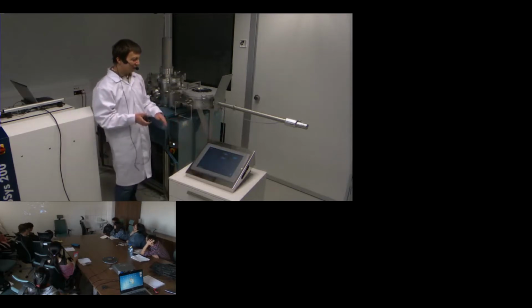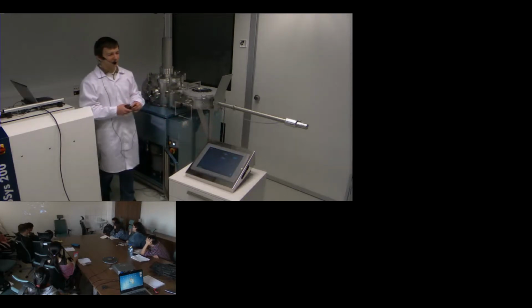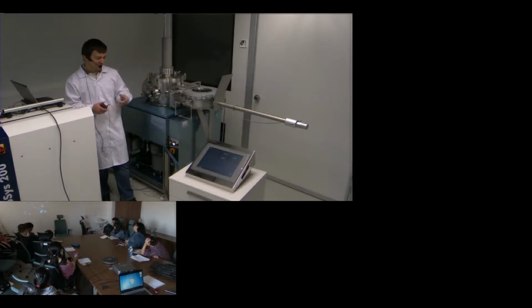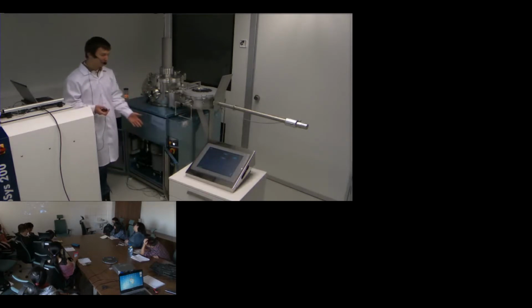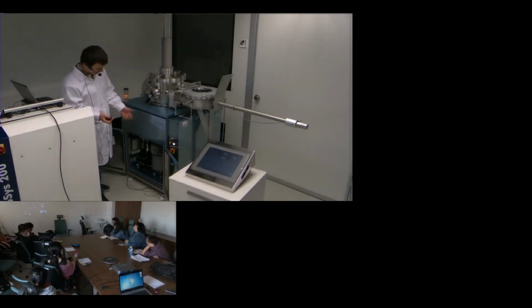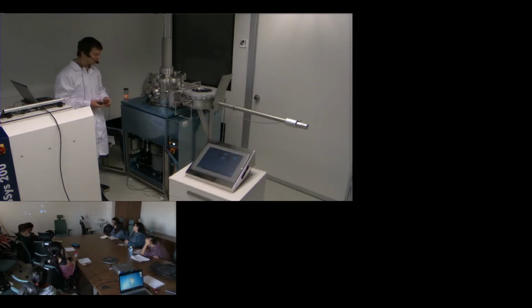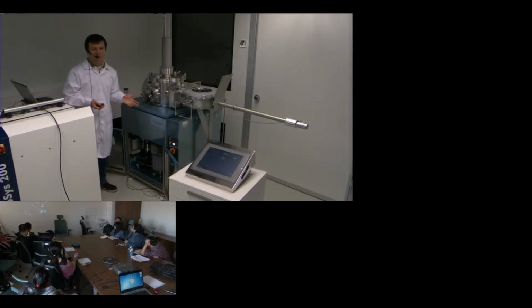Of course, this process is controlled by a computer, which is here. So you just write the recipes, which precursors should be used, how many cycles should be made, so how many atomic layers you want to produce. Of course, we have a lot of precursors here, not only for hafnium, we have for aluminum and titanium and other metals. We also, apart from water, have nitrogen, so we can form not only oxides, but also nitrides of these metals.